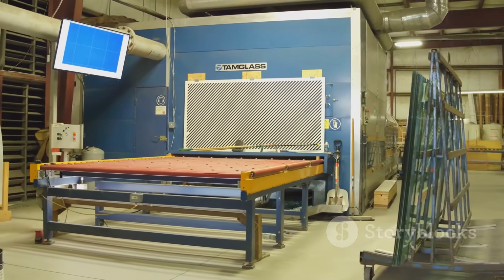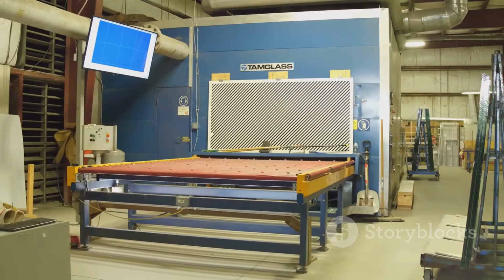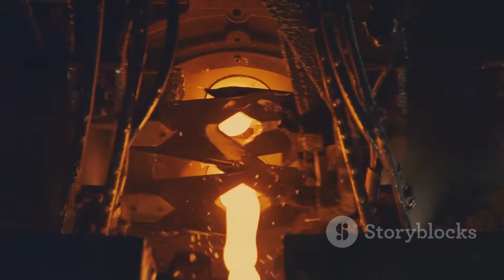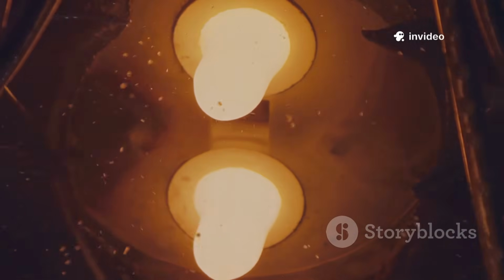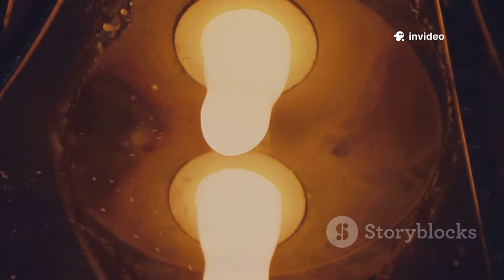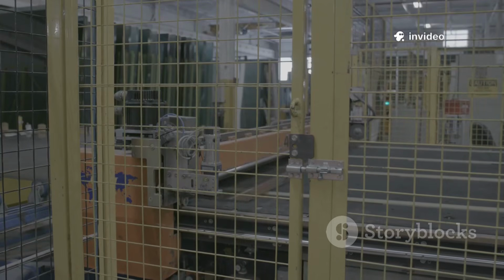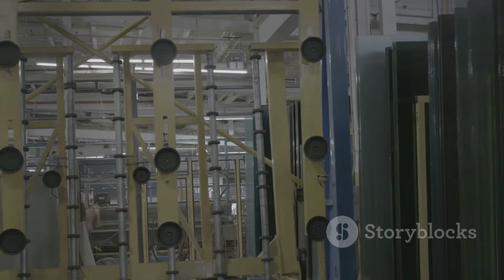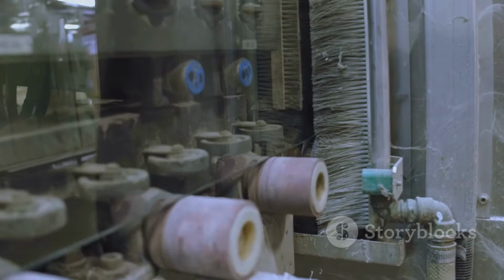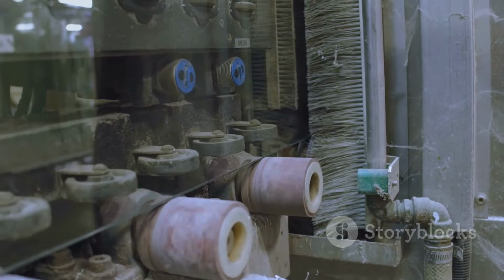Turning molten glass into flat sheets requires the float glass process. The liquid glass flows onto a bath of molten tin. Glass floats on tin, spreading out perfectly flat, like oil on water. The speed of pulling determines the glass's thickness. Faster means thinner. Slower means thicker. This process creates sheets with uniform thickness and flawless surfaces.